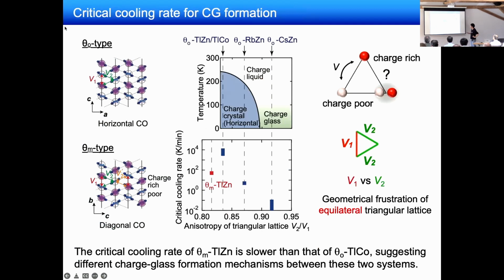Okay. So as I already discussed, this orthorhombic system can be understood by the anisotropy of the triangular lattice, V2 over V1, but the tendency of the monoclinic one does not follow this trend, which suggests different charge glass formation mechanisms between these two systems, the orthorhombic one and the monoclinic one. So we decided to investigate the physical properties of these two systems.